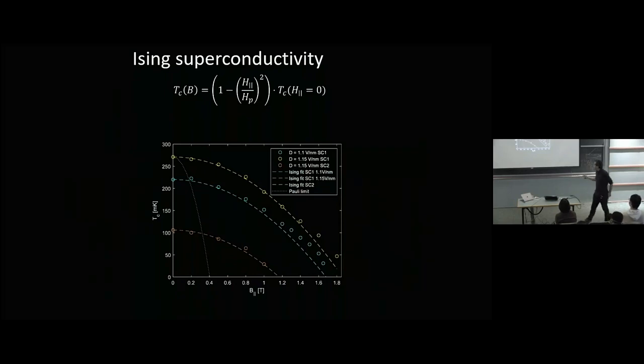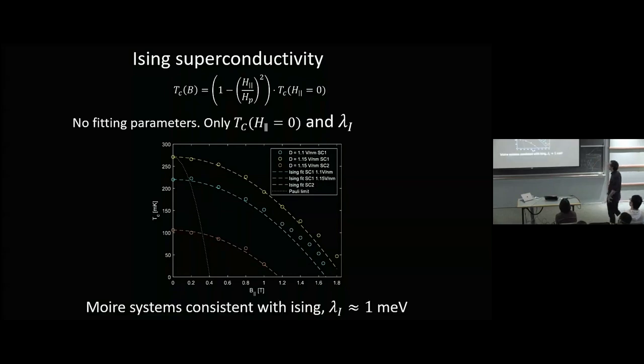And as far as I know, this is a nice system even among Ising superconductors because you know exactly what the spin-orbit coupling is, right? You measure that in situ, you can vary it in different devices, and we think that most of these superconductors on WSe2-supported graphene are Ising superconductors. If you look at the measurements that have been done, I think they're all consistent with this, but those other systems don't have a way of measuring that spin-orbit coupling.